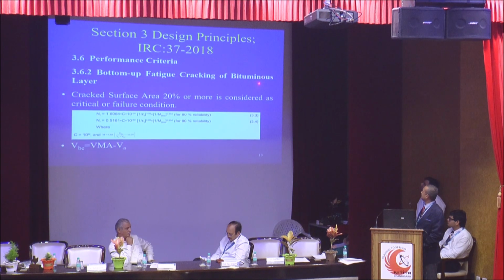Bottom-up fatigue cracking of bituminous layer. When crack surface area is more than 20%, we consider it a critical or failure condition, and this is the equation that we developed for Indian condition. And dear friends, here the term used is VBE, volume of effective bitumen.